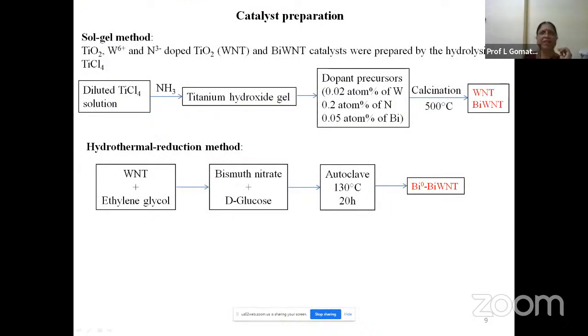So what are the preparation methods? The sol-gel method is given here. Diluted titanium tetrachloride solution is taken, and ammonia is added to it at pH 7 or 8, and titanium hydroxide gel is made. This titanium hydroxide gel is washed several times to remove all chloride ions and excess ammonium ions. And the dopants are introduced into the gel, and we have incorporated 0.02 atom percent of tungsten and 0.2 atom percent of nitrogen, and the bismuth taken for both samples is 0.05 atom percent. When these dopants are incorporated, the precipitate is filtered and calcined at 500 degrees centigrade, and the same procedure is used for WNT. For BiWNT also, we use the same procedure. So both the compounds are prepared by this technique.